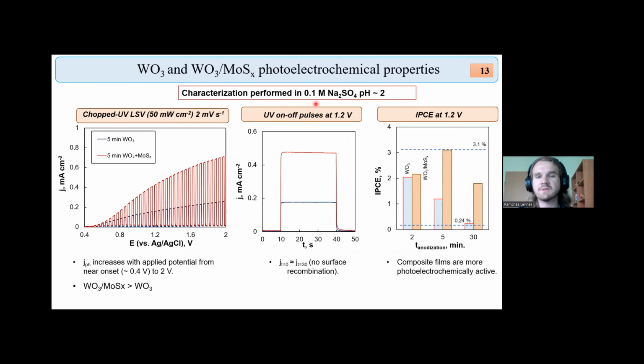And these films have been characterized for their photoelectrochemical properties. The characterization was performed in an acidic sodium sulfate solution with a 365 nanometer near UV light source. The initial experiments performed were chopped UV linear sweep voltammetry under illumination by 50 milliwatts per square centimeter. And as the potential is scanned toward the anodic direction, the UV light is also incrementally switched on and off. And this gives a good idea of how both the background current and the photocurrent depend on the applied potential. The overall result we see from these graphs is that comparing the base tungsten oxide with the composite generates far larger photocurrents, whereas the so-called dark current is similar.